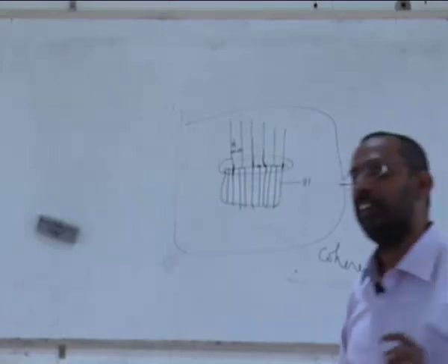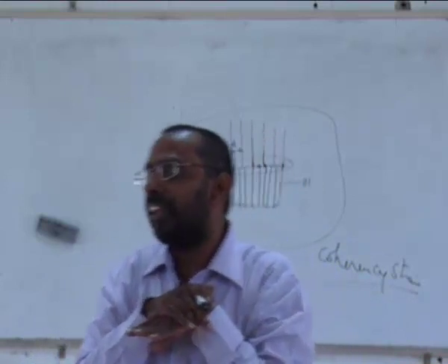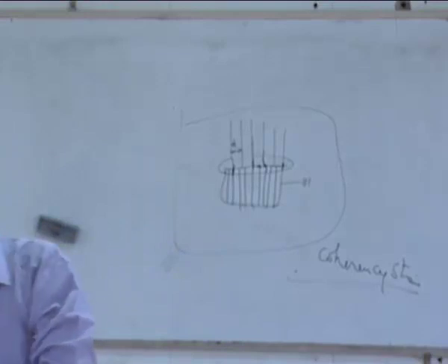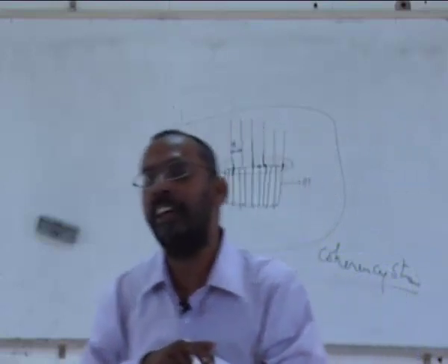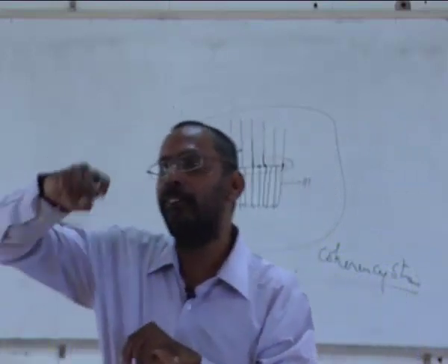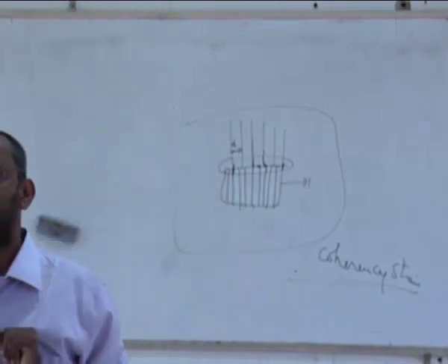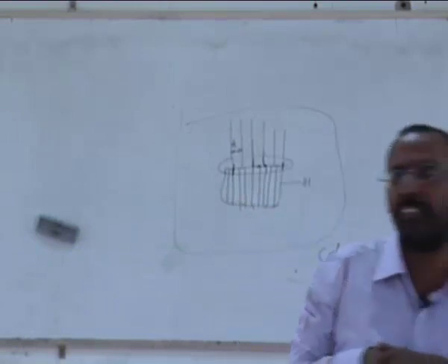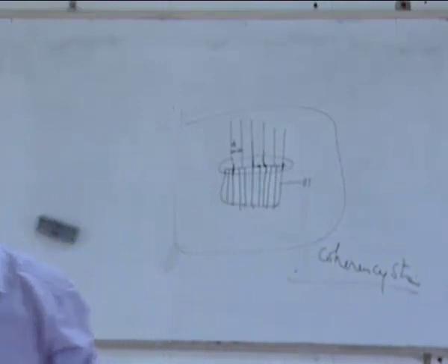And if you look at the atomic arrangement, that atomic arrangement is exactly similar to one plane of FCC. What is that plane? If I want, I will give you what is that atomic arrangement in that basal plane. You will have every one atom surrounded by 6 atoms. That is what the basal plane is, right? Hexagonal kind of. And exactly similar packing you will see in FCC in one plane. It's 1 1 1, the close packed plane of FCC.